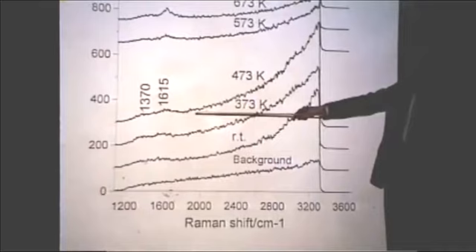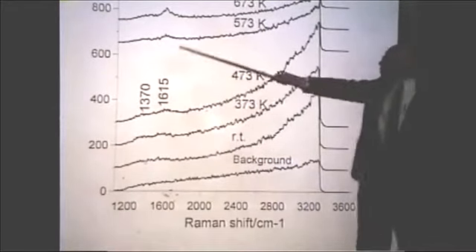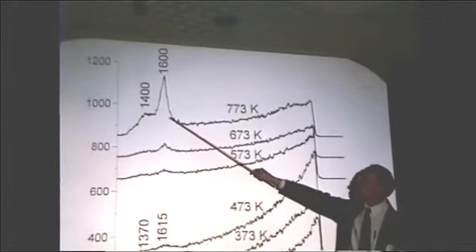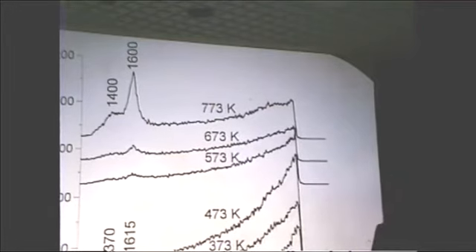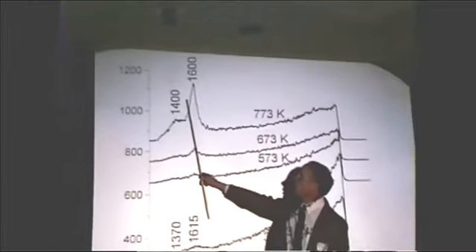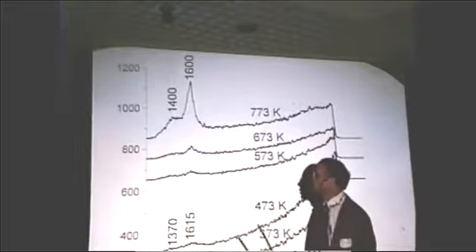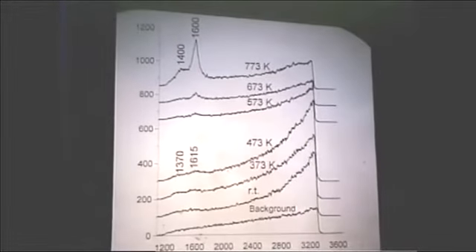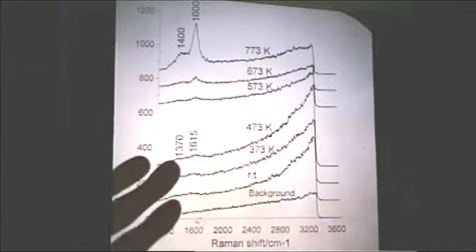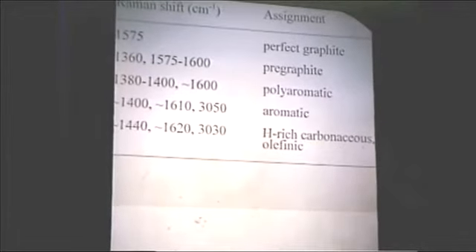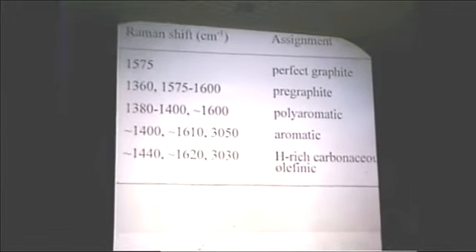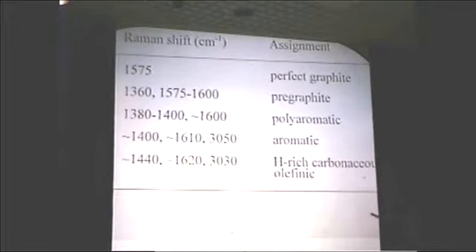If, on the other hand, we continue to expose to propylene and we heat, we eventually develop a coke band, which ends up giving us a spectrum that looks like this, where this peak is at 1600 wave numbers, so that's characteristic of polynuclear aromatic structure on the surface, but not pre-graphite. Pre-graphite we would assign, based on what we know about coke chemistry, to give us a band below 1600 wave numbers, and this one then gives us a different kind of coke than what we see on the acid catalyst. And of course you can oxidize it off and it all comes off. So what we find here is that with the Raman scattering, we can rather quickly and easily discriminate different kinds or classes of coke on the catalyst.